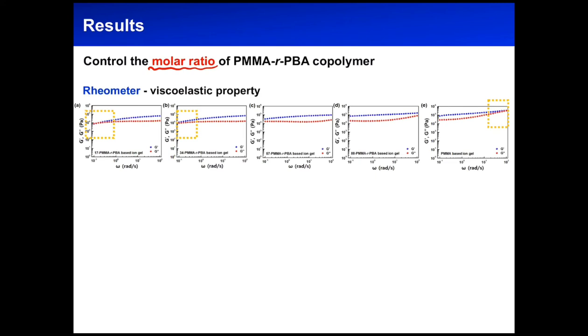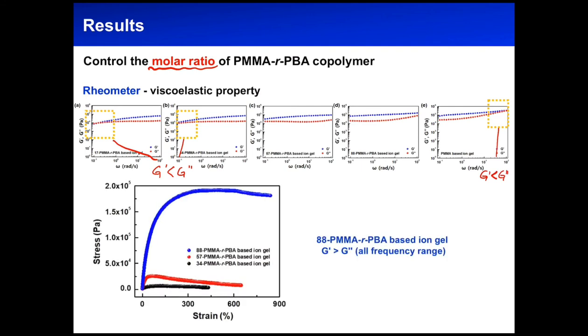Therefore, we increased the PBA molar fractions and the resulting rheological properties were evaluated by rheometer. In the high molar fractions of PBA containing ion gel, the G' is reversed by G'' in low frequency. And on the other side, if the PMMA molar fractions is more than 88%, the G' is reversed by G'' in high frequency. Accordingly, we chose 88% of PMMA-r-PBA copolymer, which shows solid state at all frequency region.